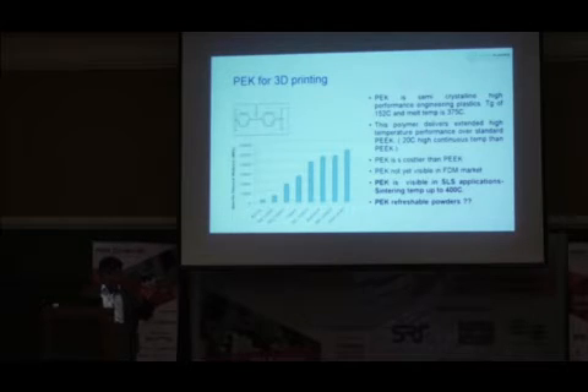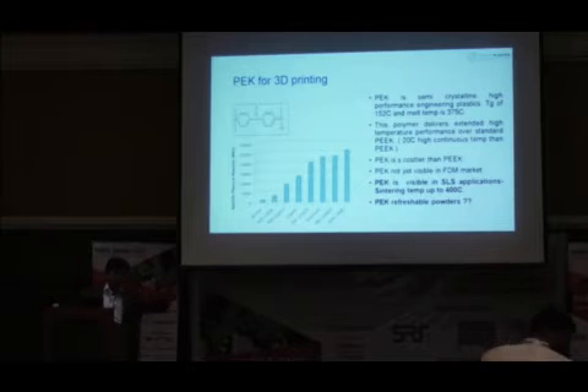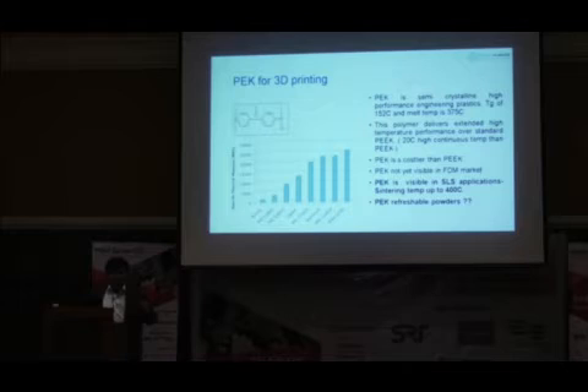This material has a higher melt temperature than PEEK. So that is one of the limitations, because when you want to process this material in extrusion for filament, you have to go up to 400 degrees C. When you want to extrude this material at 400 degrees C, you need a lot of heat control, and a lot of processing parameter control is required. That's why many people are not trying this material for filament,